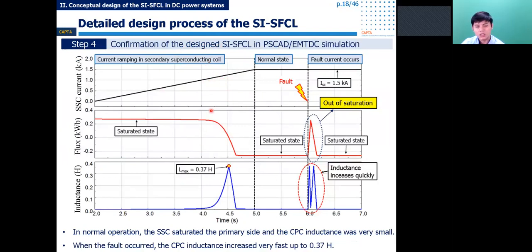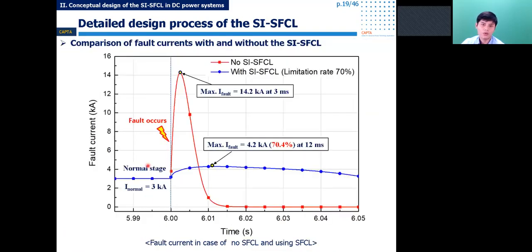As the result, here in the normal operation, the secondary coil will fully saturate the primary side with the opposite magnetic field, and then you can see the primary inductance is very small because of air core inductance. When the fault occurs, the primary side core will go out of saturation, and the inductance increases very fast up to 0.37 Henry. And here is the fault current limiting performance result. Comparing with the case of not using the SFCL, using the SIFCL could limit the fault by 70.4% with a limitation time of 12 milliseconds. So the design target of the SIFCL was already obtained.